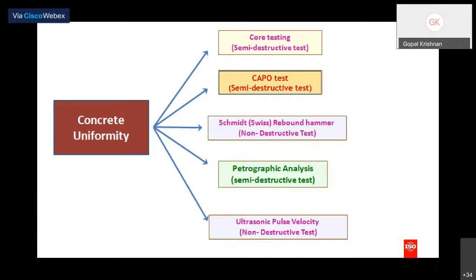The core is one of the important aspects. Then cut and pull out, which creates less damage to the structures. It's very well introduced nowadays. I am going to give the details about the cut and pull out test. Then you're all familiar with the rebound hammer and petrography analysis, understanding the matrix of the deterioration, the matrix of the cement binder, what the binding strength is, etc.